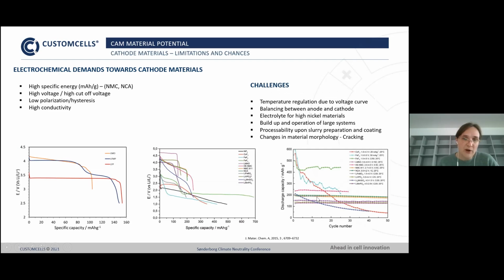If you are looking for the right cathode material, you see that they can be very, very different depending on the material. You have to make sure that even if there is a high specific capacity, this specific capacity is gained at a reasonable voltage and not at a too low voltage, or you will gain not much energy. And you also have to take into account that the specific capacity is stable over the cycling of the cell, not only at the very beginning of the cycling, but also at the end of the cycling.